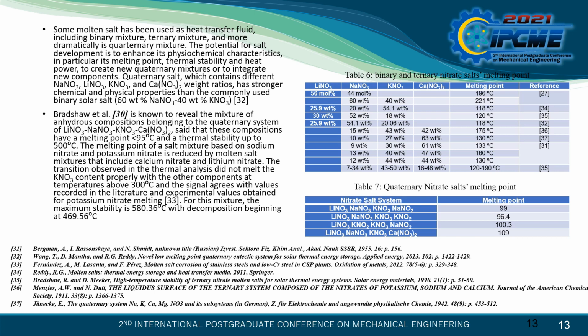By reducing the melting point, you will also improve certain thermophysical properties of, in this case, the nitrate salt. Now, Bradshaw is known to have revealed a mixture of anhydrous composition belonging to the quaternary system: lithium nitrate, sodium nitrate, potassium nitrate, and calcium nitrate. These compositions have a melting point lower than 95 degrees Celsius and thermal stability up to 500, which means a very high thermal stability and low melting point. This is very ideal to be used in a CSP plant.